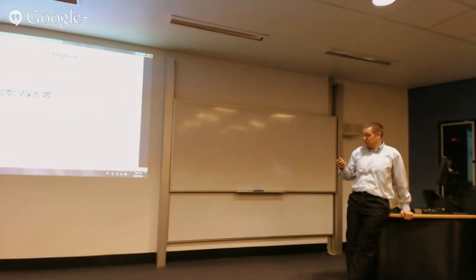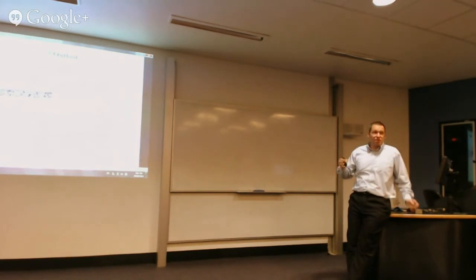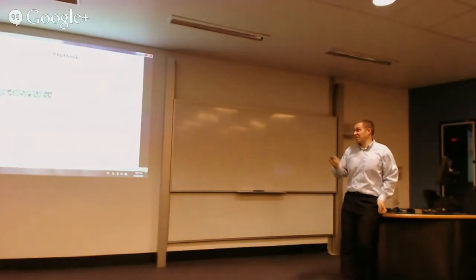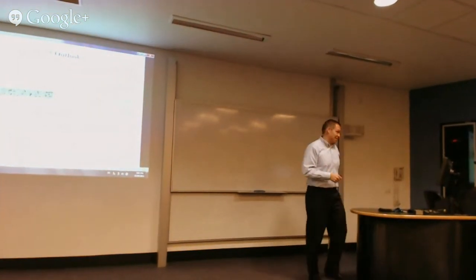More accurate would be maybe to do a CT scan and really come up with a computational model that has the same geometry as the real specimen. So this is not the geometry of the real specimen. Okay? But it's a simplified modeling approach where we try to assign to these elements the same properties. That's the common approach for how to start. And then we would refine. And maybe at the end we would say, okay, let's take a micro CT scanner to have exactly in the computational model the same geometry as the real specimen. But that's a very simplified model of how we can start to look at this.